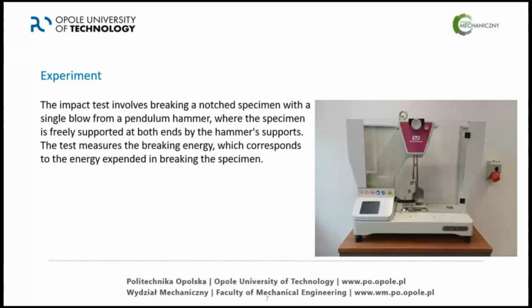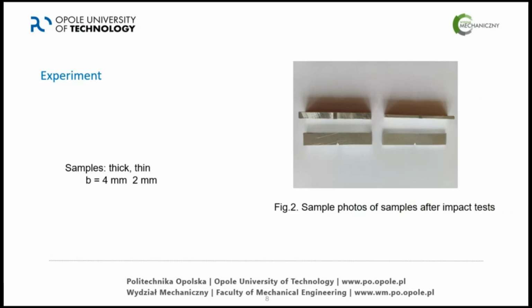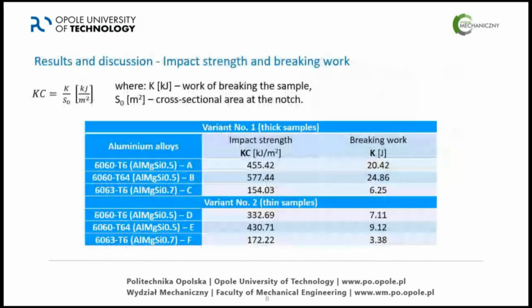At first, we did the impact test experiment. This is a typical specimen for impact strength. Here we use two kinds of samples. On the right hand, we have photos of samples after the impact test. We used two thicknesses of this material, 4 millimeters and 2 millimeters: on the left side 4 millimeters, on the right hand 2 millimeters. After calculation, we put here the mean value of 3 specimens each time, impact strength and breaking work. Now we have only the data of this experiment, 3 materials and 2 thicknesses.